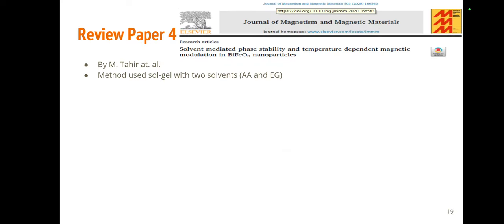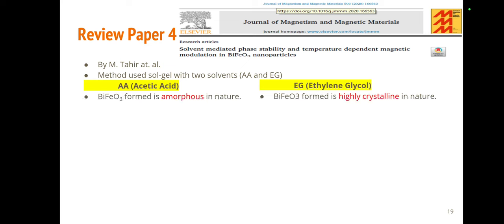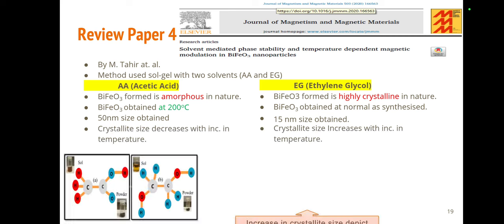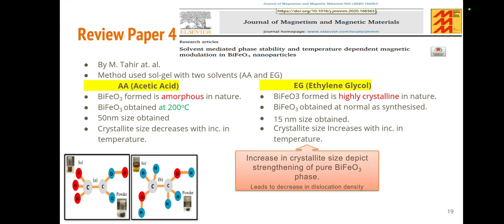In the last paper, different solvents — acetic acid and ethylene glycol — were used. Ethylene glycol produces higher crystallinity, pure phase, and smaller particle size, meaning a better crystalline phase of bismuth ferrite perovskite material can be obtained using ethylene glycol. This is because of its chelating nature, which allows it to prevent phase conversion and increase crystallite size, strengthening the pure bismuth ferrite phase.